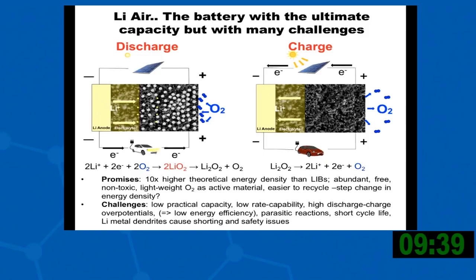So I want to end now by telling you a little bit about our work on lithium-air, which is, as I said before, the battery with the ultimate capacity, but it has many challenges. So just to remind you of what a lithium-air battery is, you have a lithium metal anode, you have an electrolyte, and you have a porous carbon structure, and the lithium can react with the oxygen that's coming in through the gas phase to form a superoxide. This superoxide ion then disproportionates to form lithium peroxide and more oxygen. And then on charge, the lithium peroxide is oxidized back to oxygen, which is then released, and the lithiums go back to the lithium metal anode.